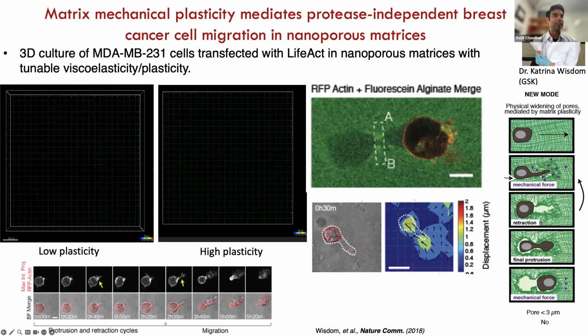And she did some extensive mechanistic studies. We see that cells are forming these invadopodial protrusions that push and pull on the matrix and eventually open up these channels that they are then able to migrate through. So this supports this idea that if a matrix exhibits a sufficient amount of mechanical plasticity, then cells can simply use forces to open up channels to then migrate through, independent of proteases.